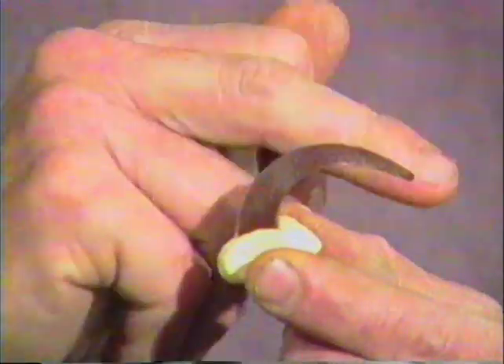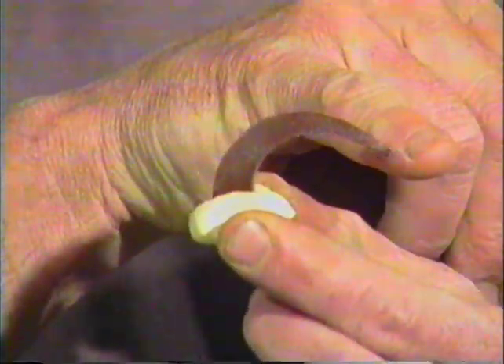Here we have the cone from the bisque, and you can see that it's nicely down with the point at about the 3 o'clock position. The bisque looks satisfactory. Took about 9.5 hours. That's a bit slow. We could have speeded it up, maybe shot for an 8-hour bisque.